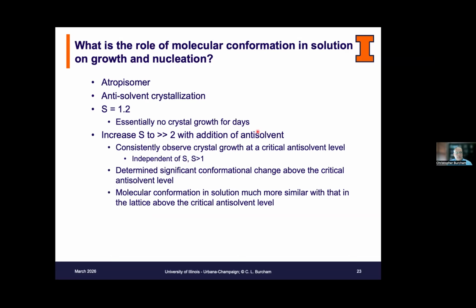In this particular case, we were doing an anti-solvent crystallization, and we started with a seeded crystallization with a 20% relative supersaturation. This is our typical starting point. The compound should have very quickly desupersaturated in solution, and we should have seen crystal growth down to where we reached the solubility limit. However, nothing happened. There was no growth for days.